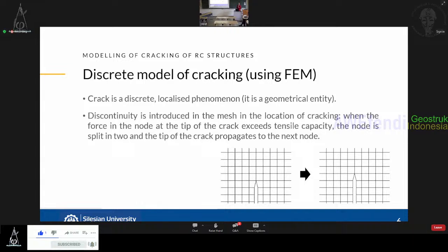So we are performing analysis in all the nodes of the mesh. And when we find a node in which the tensile capacity was reached, it means that the crack is formed in this node. We are introducing discontinuity in this node. We are remeshing our whole mesh, and we proceed to the neighboring node to see the propagation of the crack, and this way we are able to predict the path of the crack growth.